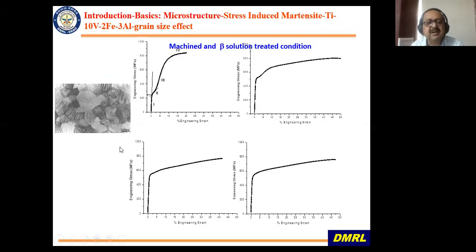Now again, another example of Ti-10-2-3, which is a beta alloy. If you beta solution treat and then start deforming it, even if you do a tensile stress test, what you, if you remember, the 10-2-3, I had shown it on the verge of stability and metastability, and so it is on the boundary line of crossing over from martensitic to non-martensitic. So it is on the borderline, and so it retains the beta phase when you quench from above the beta transus temperature. But when you start deforming it, that is, you push the material or give it a slight amount of energy, it starts transforming to martensite, and you can see this in the elastic regime of the stress strain curve, and it is known as stress induced martensite. It is called stress induced martensite because the stress has started the transformation.